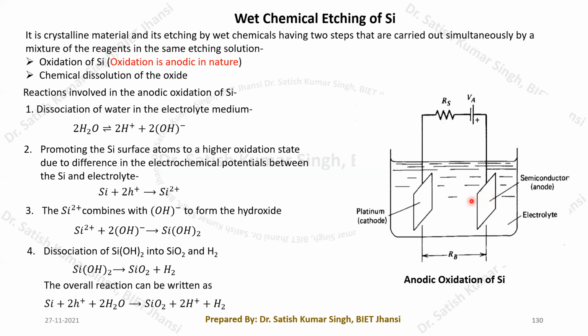A similar junction is also found for an n-type wafer surface, and at that time we have to generate the holes by some external means. That can be done either by photogeneration of the holes within this plate, or otherwise we have to increase the potential to supply holes that will be able to cross the barrier and reach the surface.